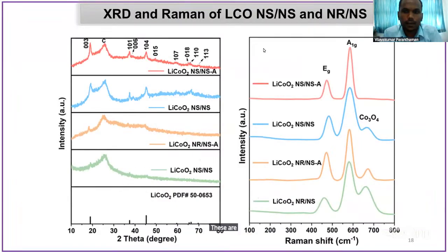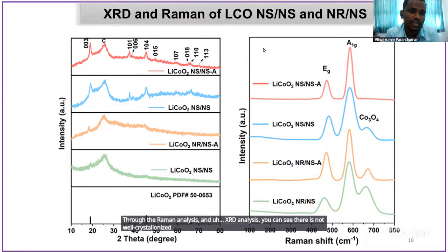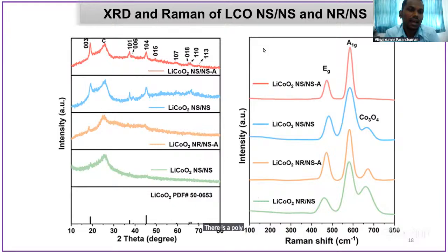These are the structural and functional structural analysis through Raman analysis and XRD analysis. You can see the material is not well crystallized. It is a polycrystalline material, where amorphous and crystalline material are combined. The carbon peak in the range of around 23 to 26 comes from the carbon cloth, not from the material. That carbon peak comes through the carbon cloth.